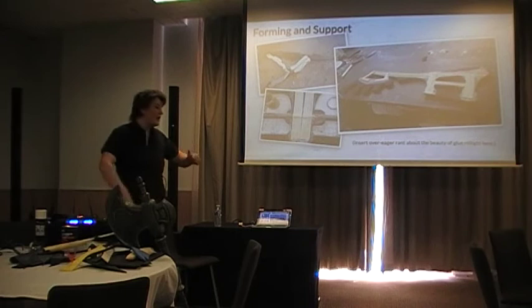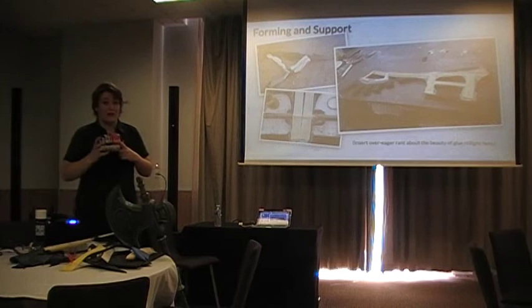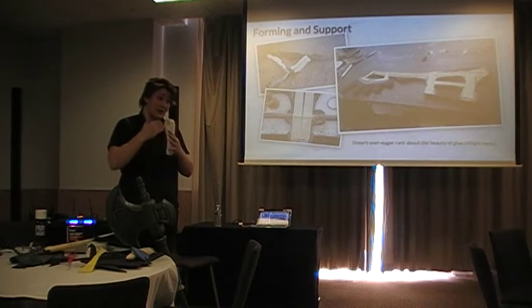Make sure that you do max that surface area out, make sure you do let the solvent release. I would definitely recommend contact adhesive, for the main reason that in most of the foam props that I would be making, the solvent can't escape when you actually create that sandwich between the two foam sections. So contact is the best because it lets most of the solvent out, and the little bit that's left just has enough time to reactivate each other's surface to get it to stick together properly.